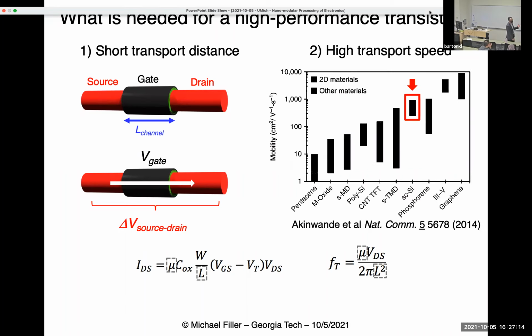Number two is a high transport speed. You want it to be moving quickly over that short distance, right? If you can combine the two together, then you generally get a good device. And this is a plot of mobility, basically speed of charge carriers through different materials. And it turns out silicon's really good at this. That's one of the huge benefits. It's not a bad semiconductor. A lot of things people have tried in more recent years are worse than silicon in terms of the speed at which charges transport in the material. So we need to get nanoscale channels and high mobility materials like silicon. There's some stuff you need to also take care of in terms of the interfaces. I will not discuss that any further.